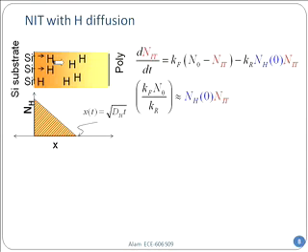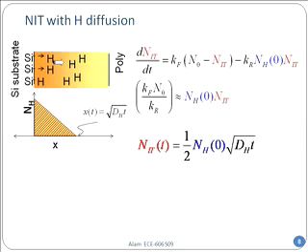Now, where will the hydrogen come from? This is coming from because bond got broken. So, the number of bonds that got broken is equal to the number of hydrogen that was released in this oxide region. So, therefore, I can write this following statement and see whether you agree with this statement. NIT, number of bonds that got broken, is equal to the area under this curve. Half, you see, triangle, right? Half. NH0 is the ordinate, and for time t, it got DHt is how far it diffused, the hydrogen how far it diffused.